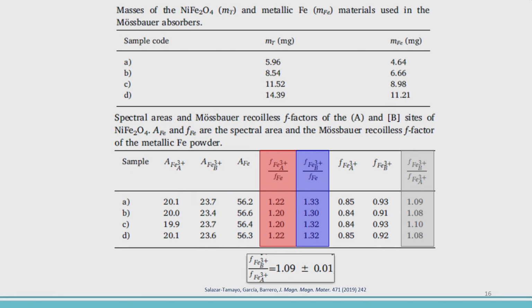I want to say that this value is different from the value that we found for magnetite. So please be careful when you use it, because we normally do the following when we want to quantify the iron in a sample. We always assume F equals 1 if we do the experiments at room temperature. This assumption that F equals 1 is valid only at very low temperatures, where F is almost equal to 1. But if we do the experiments at room temperature, F is not equal to 1.